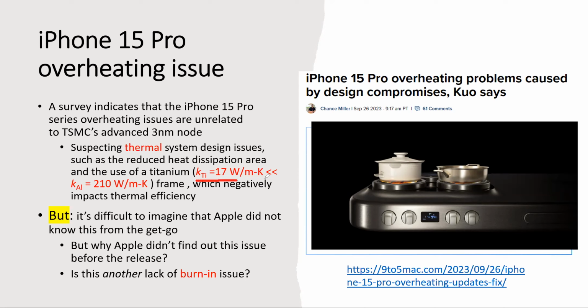You know, this is data that I dug out. Titanium's thermal conductivity value is 17 watts per meter Kelvin. 17. If you look at the aluminum case, that's 210. All right. So this is more than one order of magnitude reduction in thermal conductivity. If you look at a cell phone, everything inside, you can imagine that here you have a lot of heat generation. Eventually, it would come out. Eventually, the heat has to be absorbed by the casing, and then the casing goes to the air, right? No matter what you do inside.